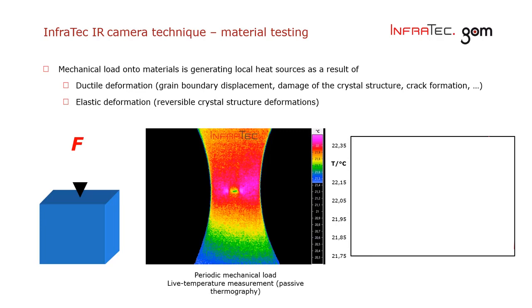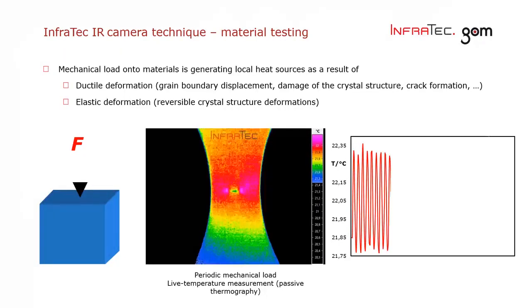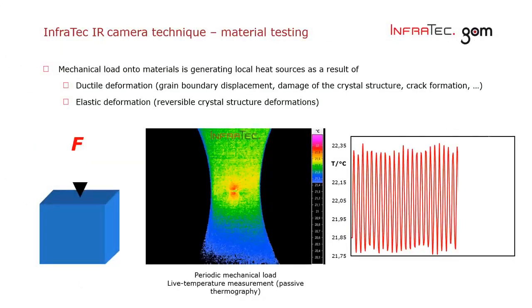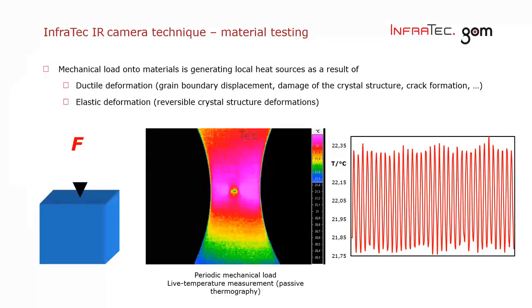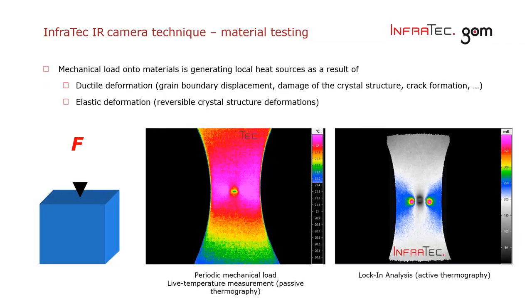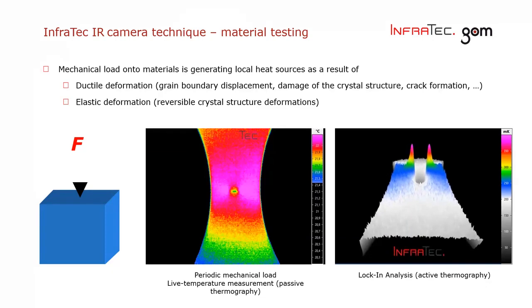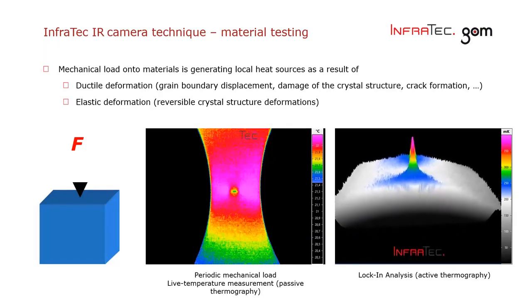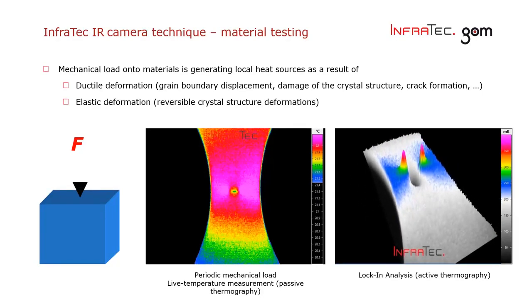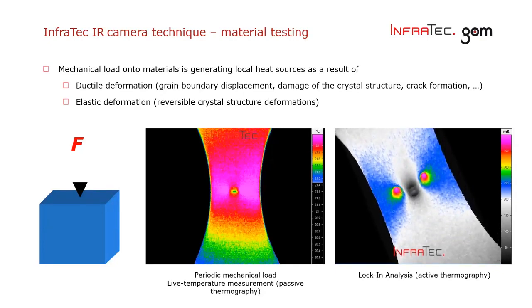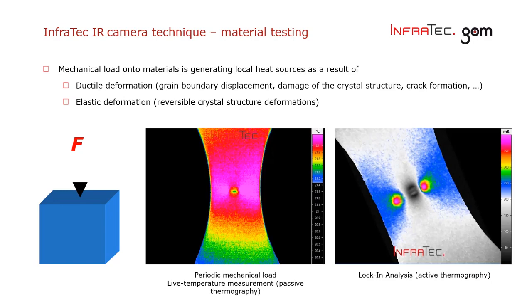You see this on the live infrared streaming of a sample which is periodically mechanically loaded by a force, and you can directly see the temperature changing by about 0.5 Kelvin during the unload and loading cycles. We can use these data as well for a special analysis based on lock-in, where we just point out the differences of the temperature under load and unloaded situation of the sample. We also can see this in 3D, just to have an imagination what is the real difference relative to the different positions or locations on the sample. In the next few slides we will see also a stress test analysis, but not with periodic load, but with a one force load until crack.